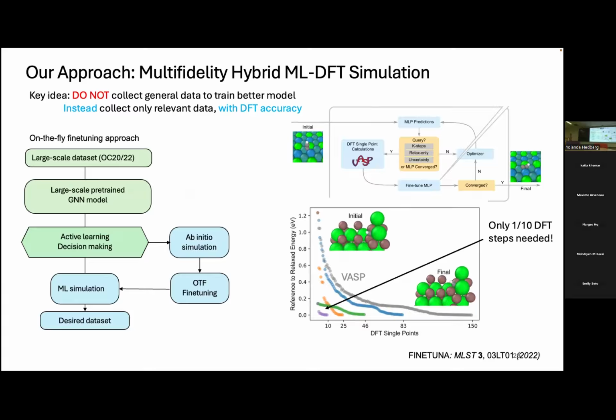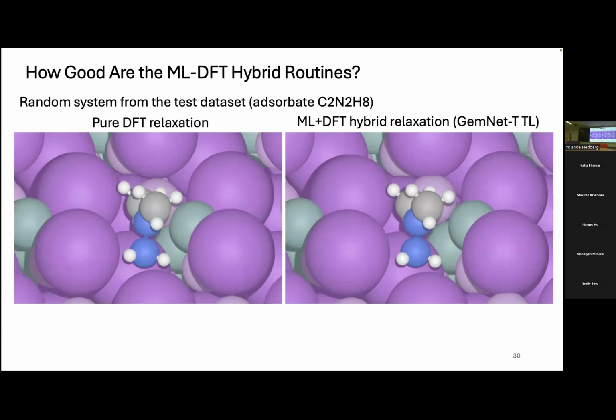But instead of directly using everything in pure DFT or everything in pure machine learning, we have an iterative loop where, for highly uncertain regions, we use DFT to get the data, and these data are going to retrain the model to be able to get much faster results to the final conclusion.